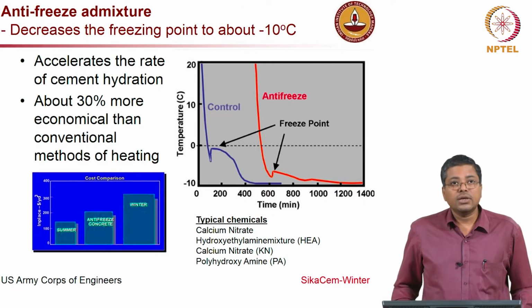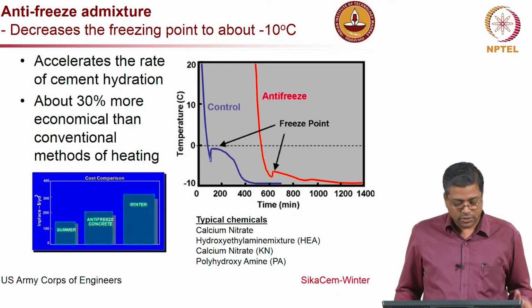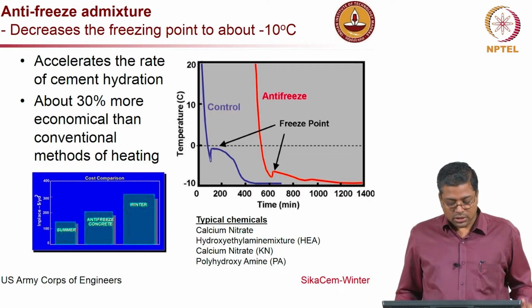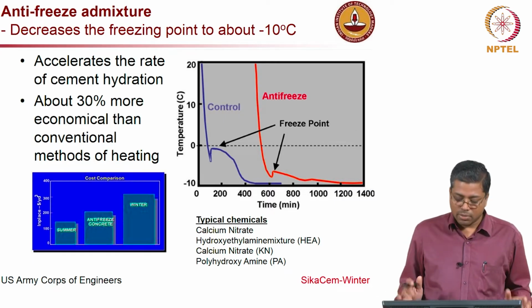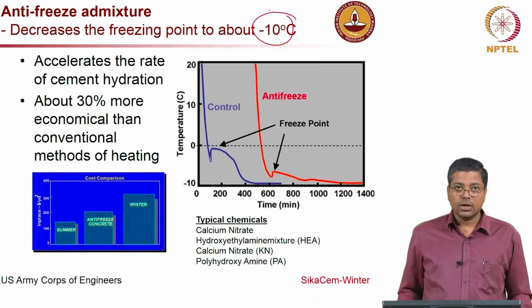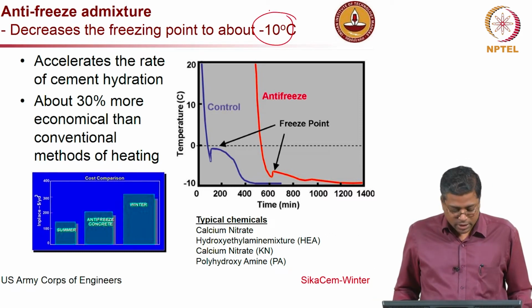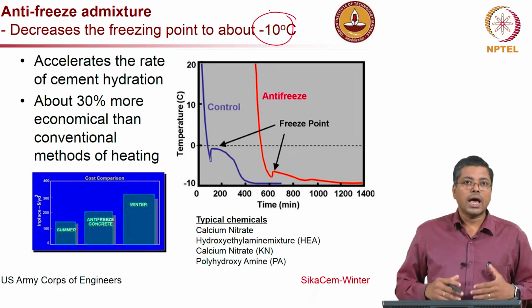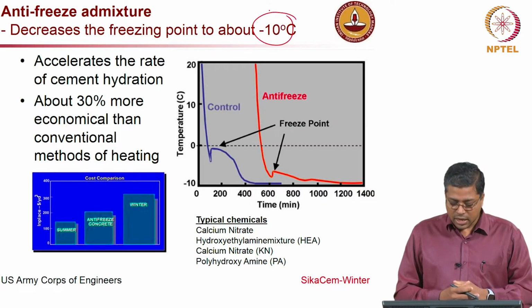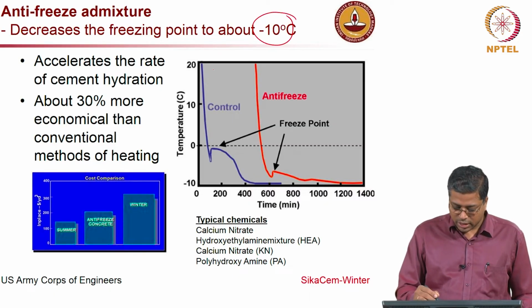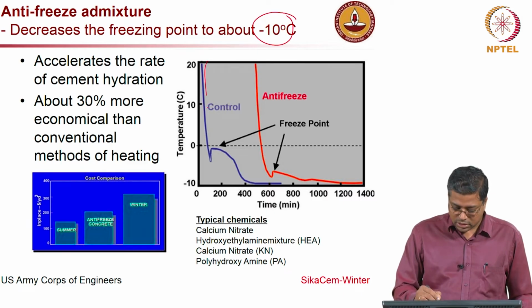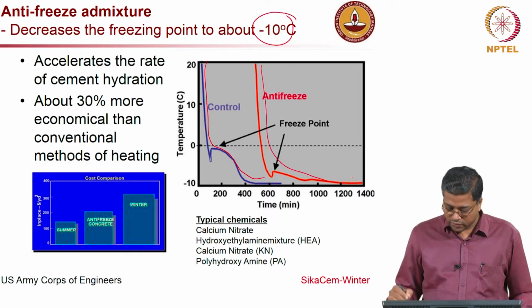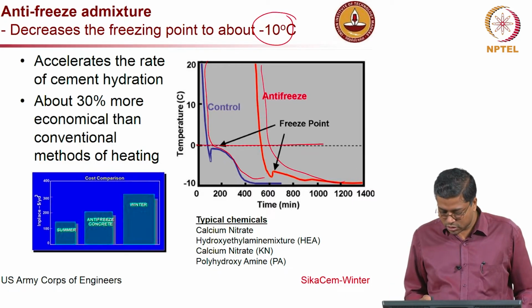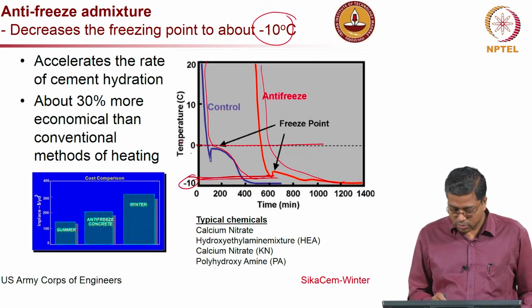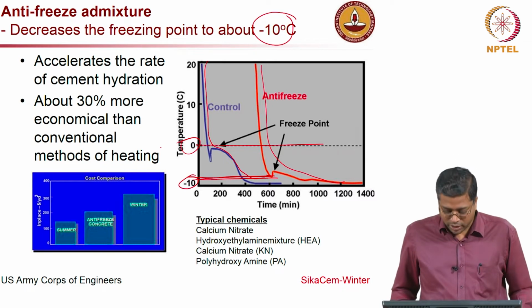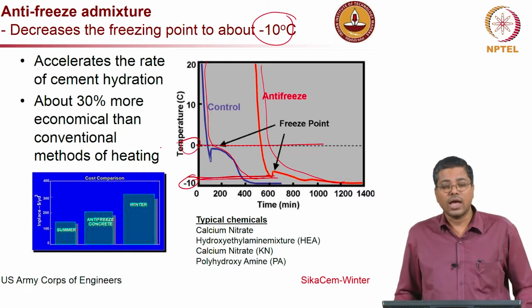And antifreeze admixture is another technology where the addition of these admixtures reduces the freezing point of the mixing water by about 10 degrees Celsius. Okay. From 0 it might go to -10. Because of that reduction you have more water available for the hydration reaction, and you can see in this graph, the control case has no antifreeze admixtures, and the red one with antifreeze, you can see there is a drop from 0 to about -10. So, that is the reduction in the freezing point of the two systems without and with antifreeze admixtures.